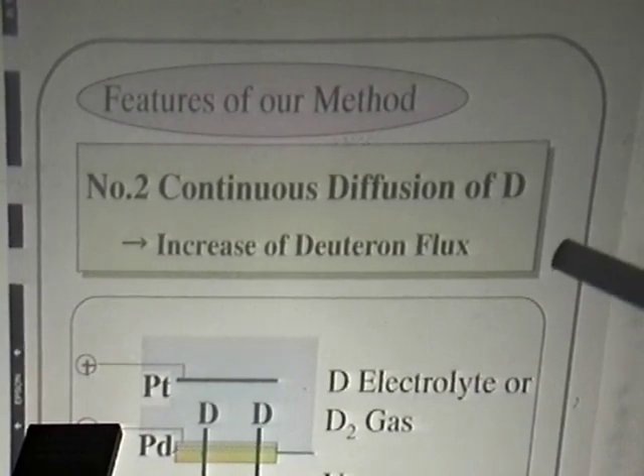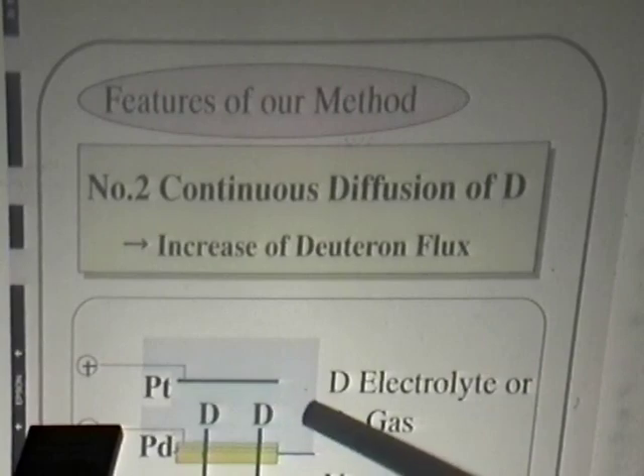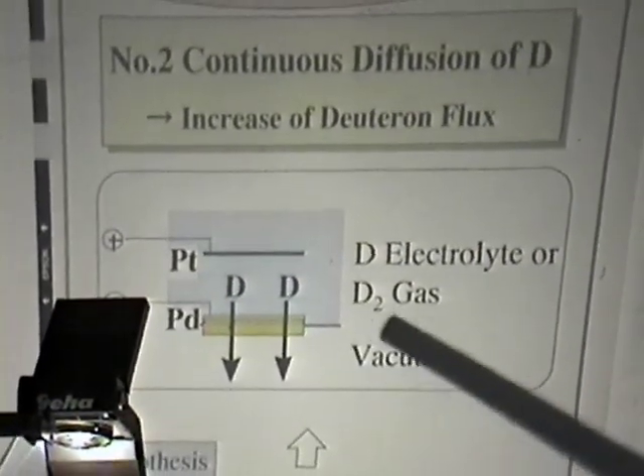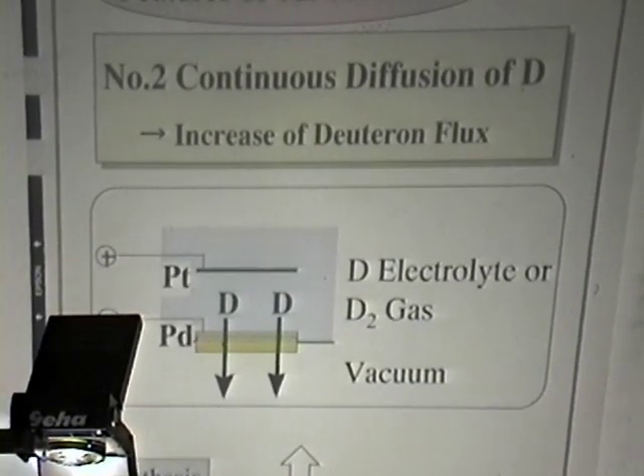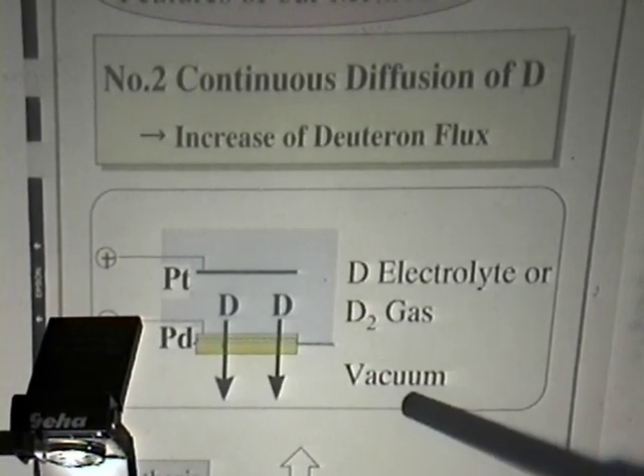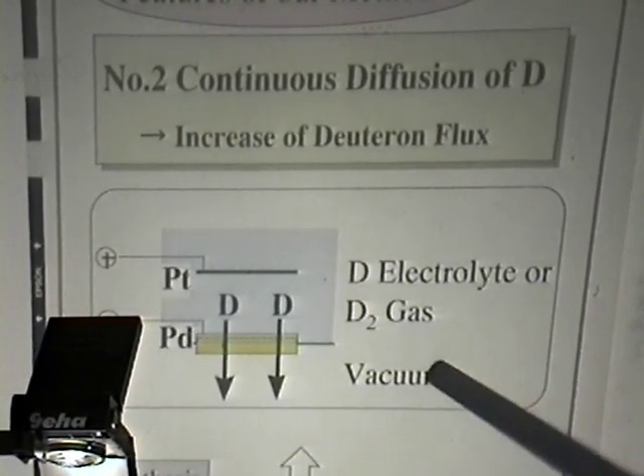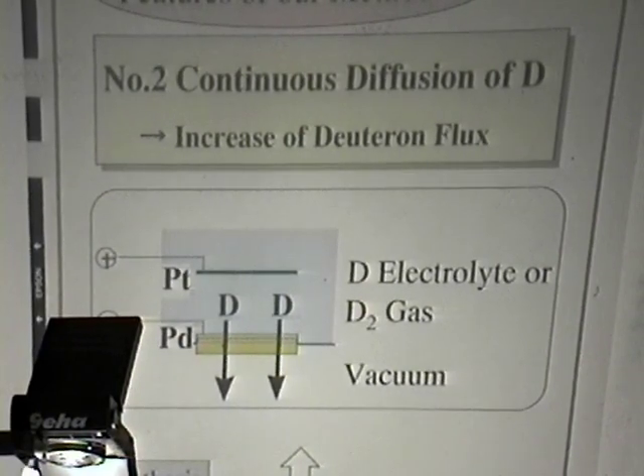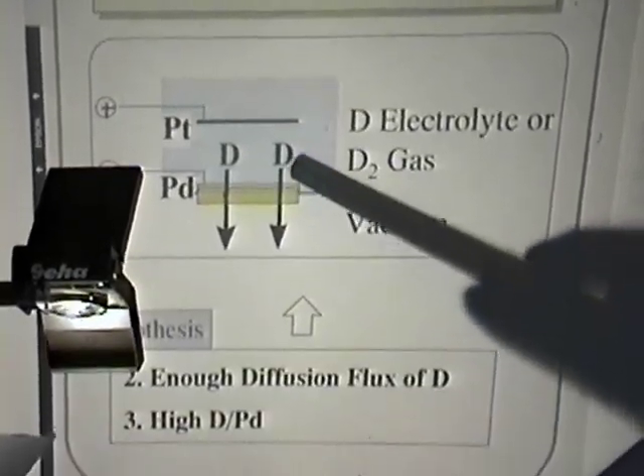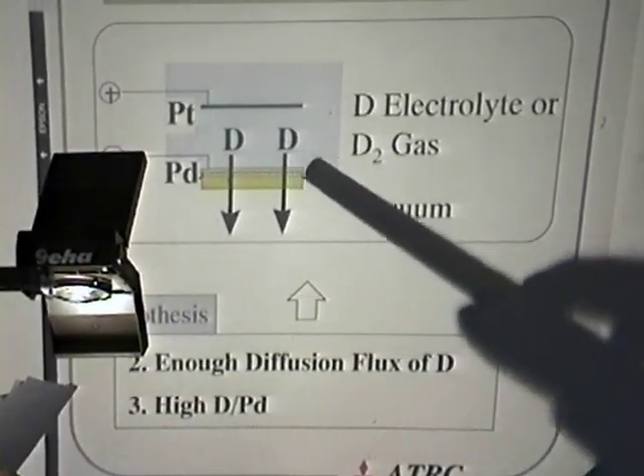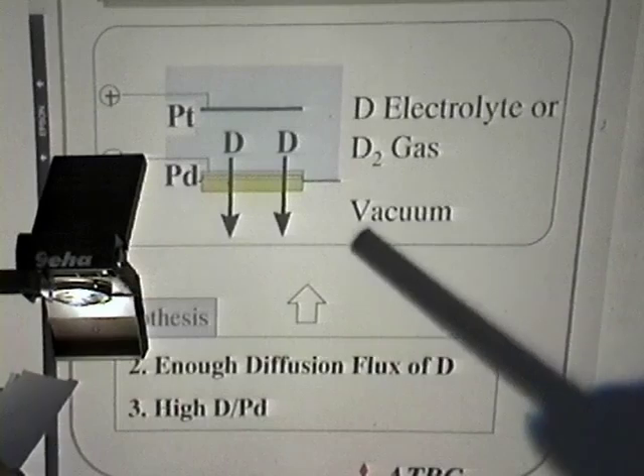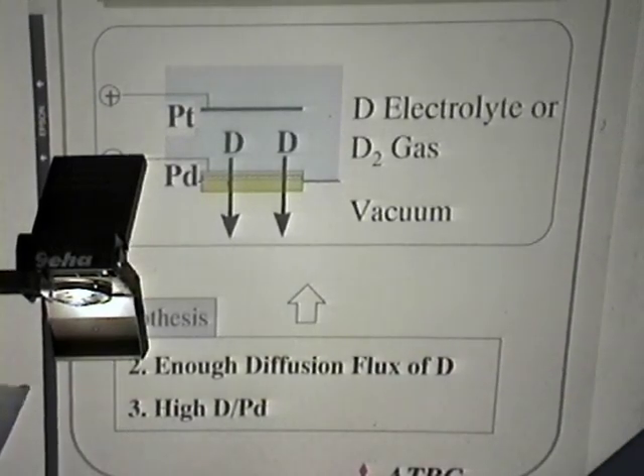Next, the features of our method. The next feature of our method is a continuous diffusion of deuterium. This is palladium sheet, which contains low work function material. On the upper side, deuterium atoms are electrochemically loaded or loaded by D2 gas pressure. On the vacuum side, the lower side, we keep a vacuum condition. So we have a continuous flow of deuterium atoms from upper side to lower side. With this configuration, we can provide enough diffusion flux of deuterium.